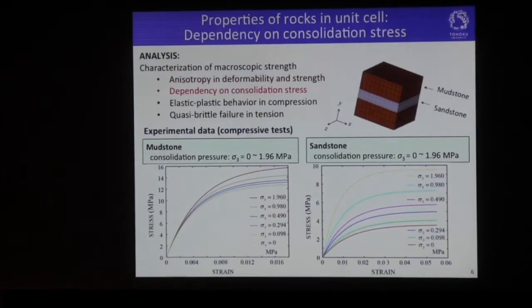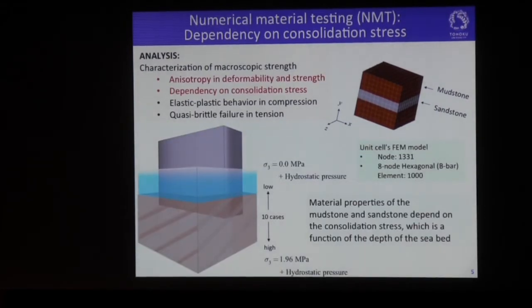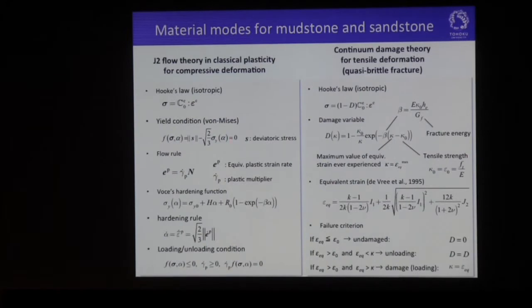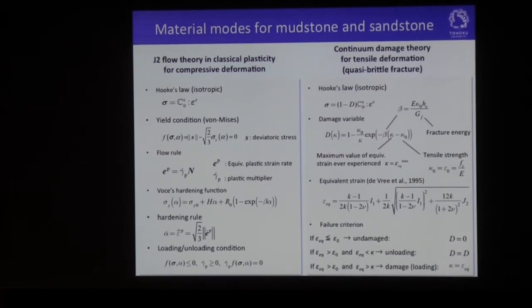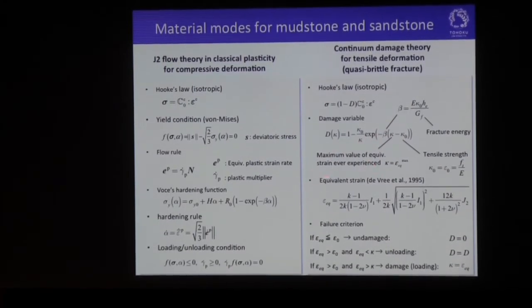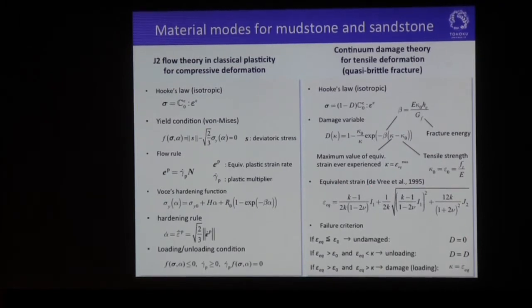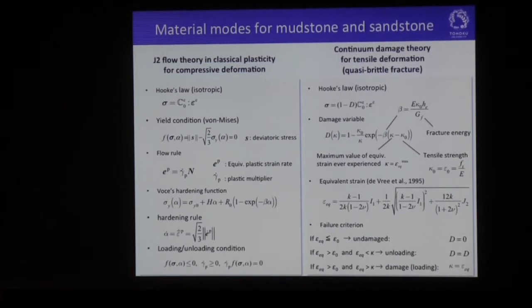Okay, so for that purpose, we first introduced the material models for mudstone and sandstone. For the compressive deformation, we employed the classical theory of plasticity, that is J2 flow theory. This equation is very standard, so we don't need to explain the detail. But for tensile deformation, we employ the continuum damage theory to represent the quasi-brittle fracture. Here is the Hooke's law, which involves the damage parameter here. This damage variable is a function of fracture energy and the tensile strength. And here we have the maximum value of the equivalent strain ever experienced. Here is the definition of the equivalent strain given by this. And also we provide the failure criterion like this.